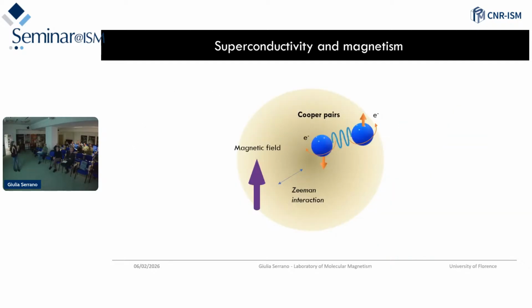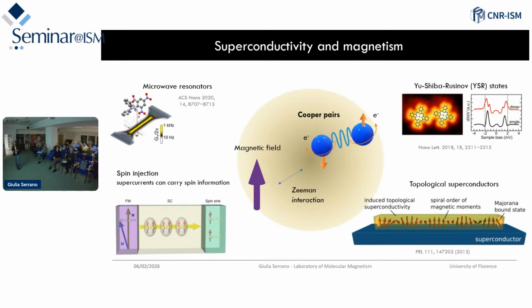So why? First of all, investigating magnetic molecules, magnetism, and superconductivity. We know that magnetic fields interact in a quite nasty way with superconductivity, because magnetic fields tend to align in the same direction the two spins of the electrons of the Cooper pairs that characterize the transport of the superconductor. But out of this nasty interaction, there are a bunch of very interesting phenomena that we can observe. For example, we can couple a ferromagnetic material to a superconductor, and we can try to inject, other than an electron current, a spin current that can then drive without resistance.